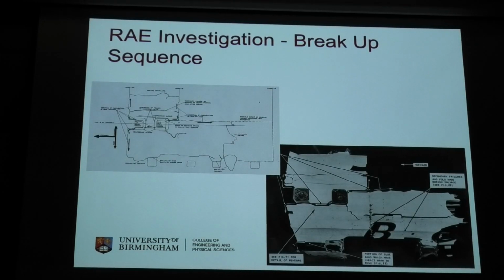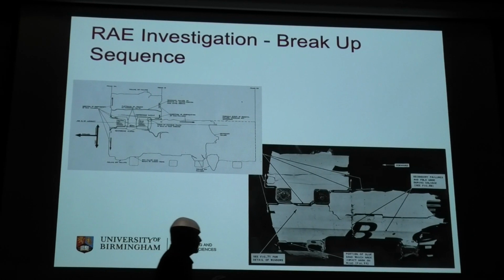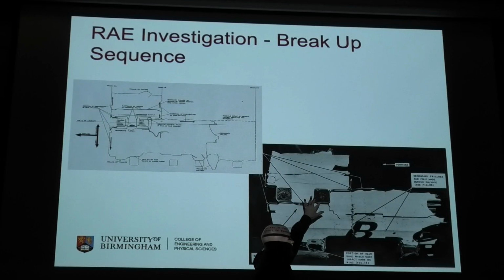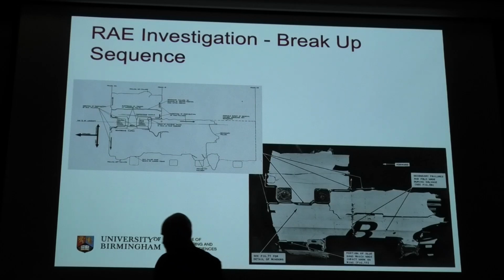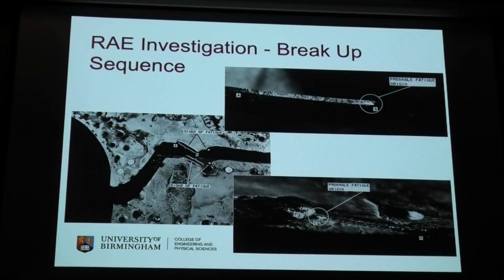They got it all the way back to one piece, just behind the rear aerial direction finding window, which were effectively slightly larger cutouts, just like windows. But that was for the avionics rather than for passengers, and it came out of the back of there. And when they looked at it, they could see that there was a bolt hole. The crack grew out of both sides of the bolt hole, with evidence of fatigue going both ways. The crack grew to its critical length, and the cabin burst open.